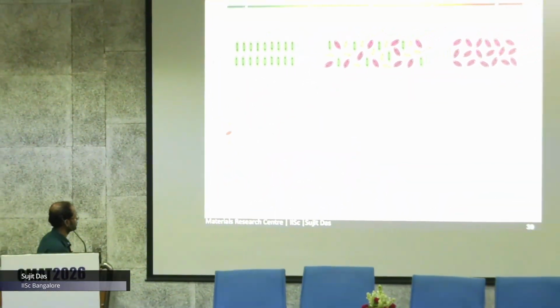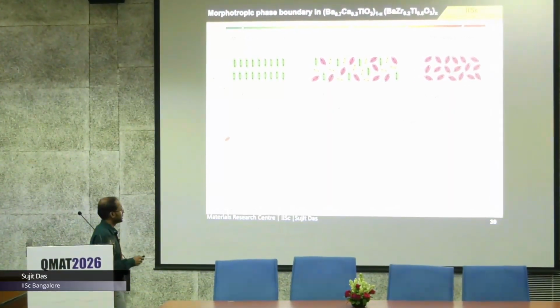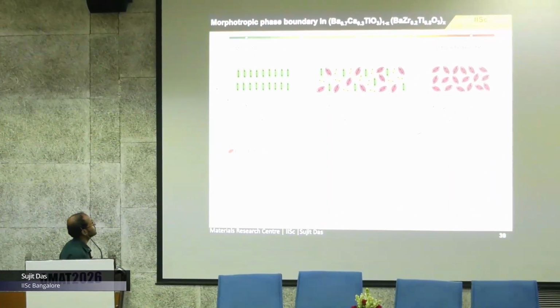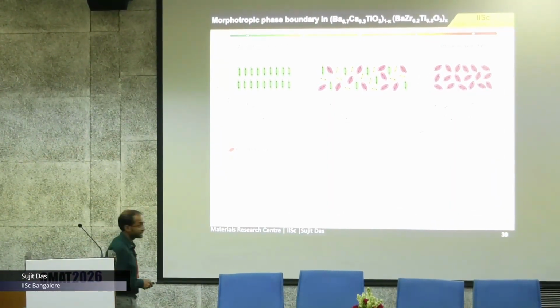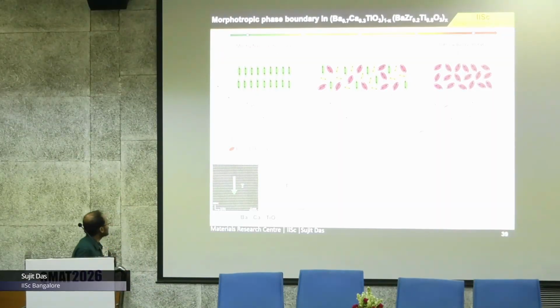So for example, x equals 0, it can have a tetragonal phase. Now if we mix 50-50%, it can have a morphotropic phase with rhombohedral, orthorhombic and tetragonal phases. And if we go to x equals 1, we can have a diffuse relaxor type of phase. And how do we prove that?